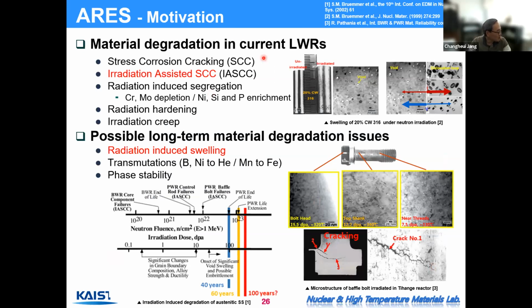Like many other structural materials, stress corrosion cracking is one of the issues for corrosion resistant materials like stainless steel. Especially in the nuclear power plant, we have an additional stress corrosion cracking issue called irradiation assisted SCC. In addition to that, it is known that austenitic stainless steel has many good properties, but unfortunately, if this austenitic stainless steel is irradiated at relatively high temperature, like 500 degrees centigrade, it actually has volume changes. This one is called swelling. And this swelling is one of the key determinant properties of austenitic stainless steel, and it limits the long-term use of austenitic stainless steel when a large amount of neutron irradiation and high temperature is expected.